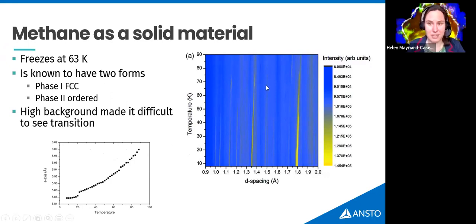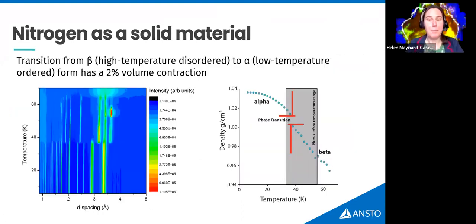And so I was able to look at methane, and again I should say that this is hydrogenous methane. So we do get a larger background, which is why the data isn't going to be as pretty as the nitrogen data I'm going to show you, but you're still able to track the unit cell, and you can see that this jump here equates to a phase transition that's known. This is phase 2, and then it jumps to phase 1. So that's less interesting in a way because that's not over Pluto temperature scales.